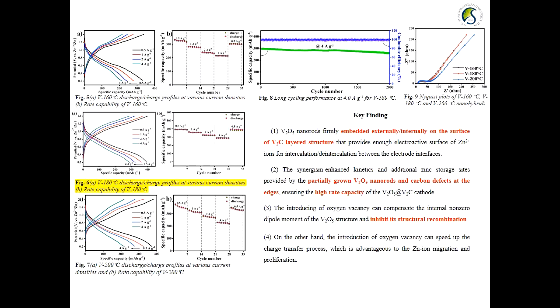So the key findings of this research is that the V2O5 nanorod is firmly embedded on the surface of V2C and provides enough electroactive surface for Zn2+ ion intercalation and deintercalation between the electrode interfaces. The synergistically enhanced kinetics and additional zinc storage sites provided by the partially grown V2O5 nanorods and carbon defects at the edges ensure the high rate capacity of the V2O5@V2C cathode.